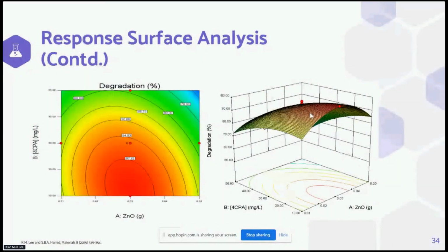Another example: these 2D and 3D contour plots show the interactive effects between the concentration and the catalyst loading while keeping the solution pH constant. The degradation percentage increases with increasing catalyst dosage up to an optimum mass, and then decreases with excessive loading. This is due to the availability of sufficient active catalyst and no aggregation occurring for the zinc oxide particles. At higher dosage and also at higher concentrations, the screening effect hinders the absorption of photons on the catalyst surface, and therefore the degradation rate will reduce.